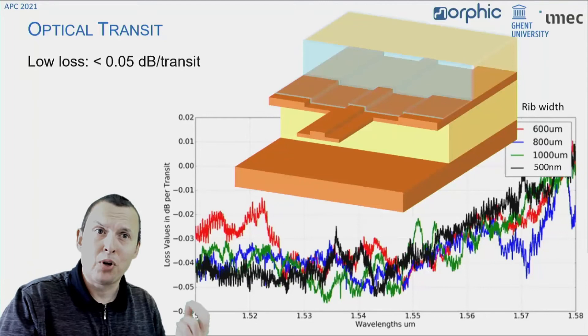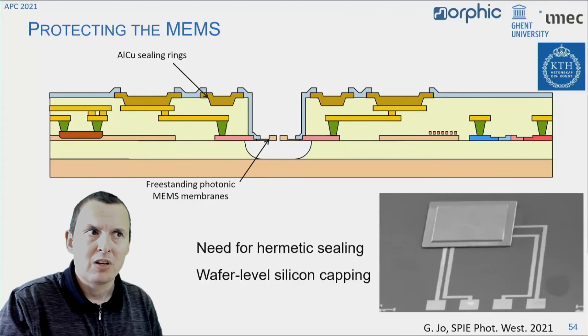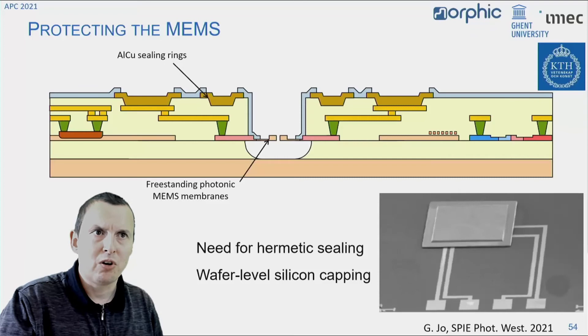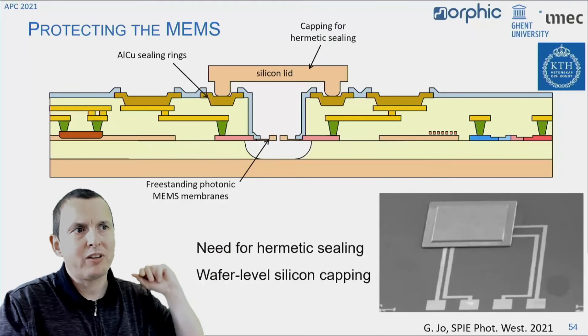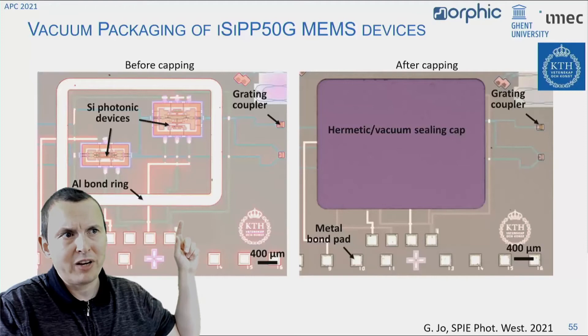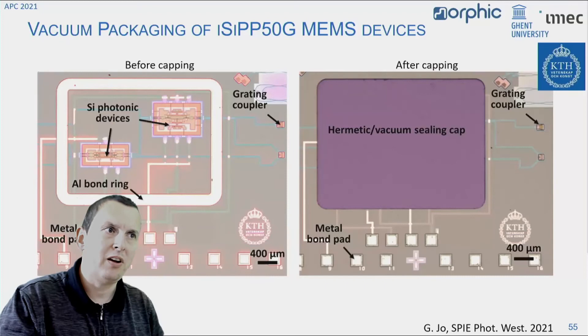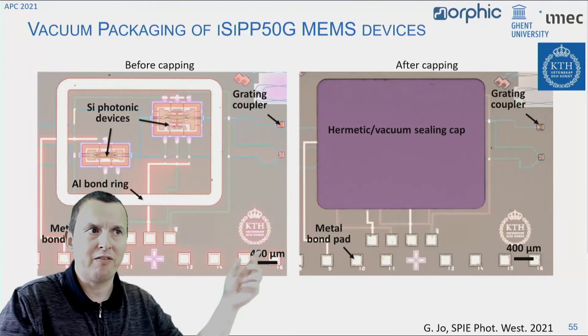Now these devices are quite useful and they're low power because they're electrostatically actuated, but there's quite a bit of challenges. And one of them is that they're essentially exposed to air, while the rest of the waveguides that are not in the MEMS cavities are covered in an oxide cladding. So that means that we have on a larger circuit quite a lot of transits between these air clad devices and oxide clad devices. And that means that this transit needs to be properly engineered, not just from an optical point of view, but also from a processing point of view, to make sure that when we process these devices, that the attack of the buried oxide and the attack of the top cladding does not destroy the devices that have to be oxide clad.